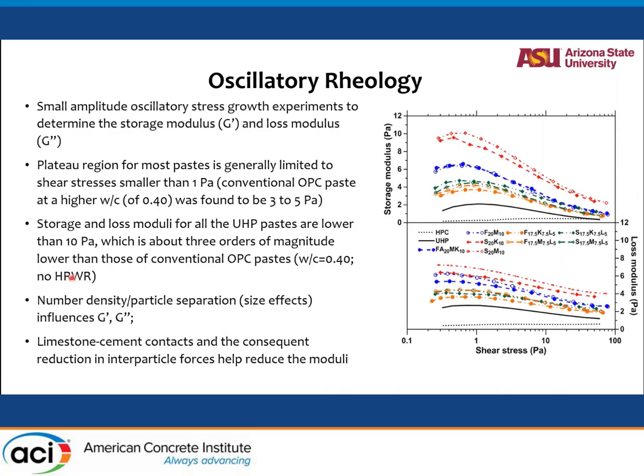We did oscillatory rheology, stress growth experiments to determine storage and loss modulus. You see that the plateau region for most pastes, which is roughly the storage modulus, is generally limited to shear stress less than 1 Pascal. Conventional OPC paste had those values to be 3 to 5 pascals. Storage and loss modulus for all UHP pastes are lower than 10 pascals, which is about 3 orders of magnitude lower than those of conventional OPC paste, without water reducer, of course.